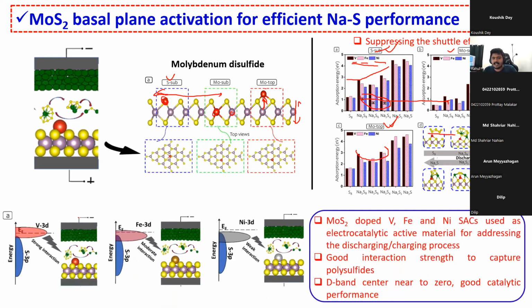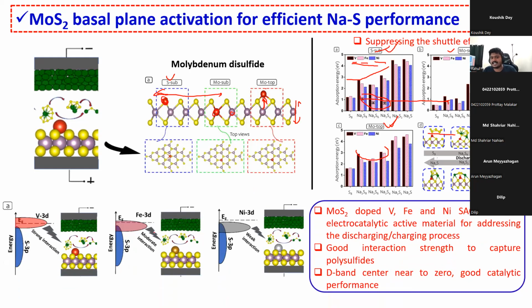Now, this is the first time we are doing this analysis for a battery, and this is a d-band center analysis. You might know that the d-band center is a very good descriptor for understanding the catalytic performance of a substrate. So basically this is the valence band, this is the conduction band, this is the Fermi level. If the d-band center of the transition metal is very close to the Fermi level, then the binding energy will be higher. If the d-band center is very far from the Fermi level, the binding energy will be lower.